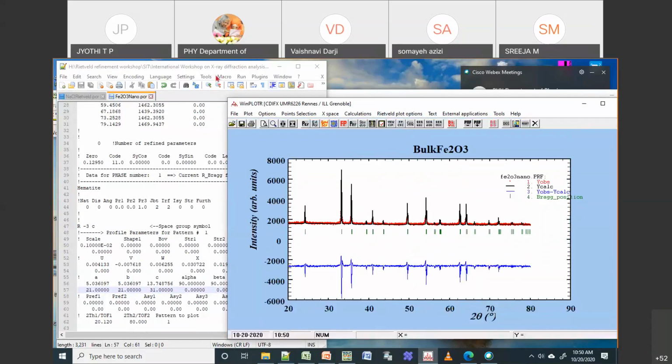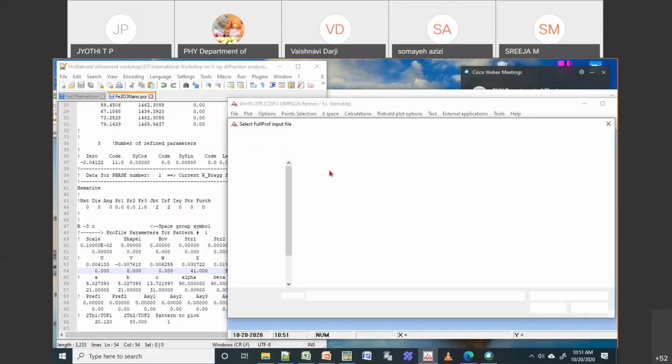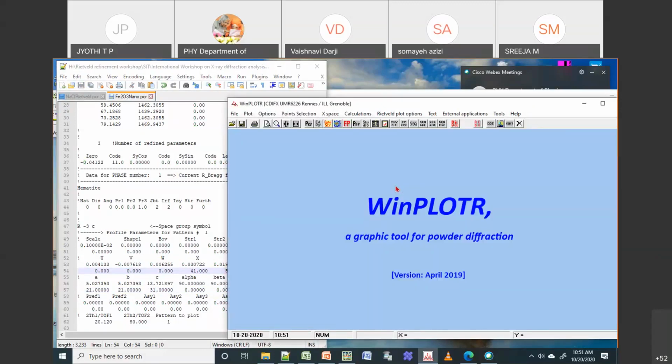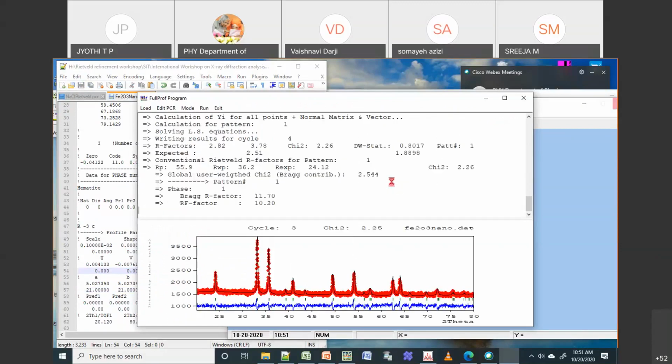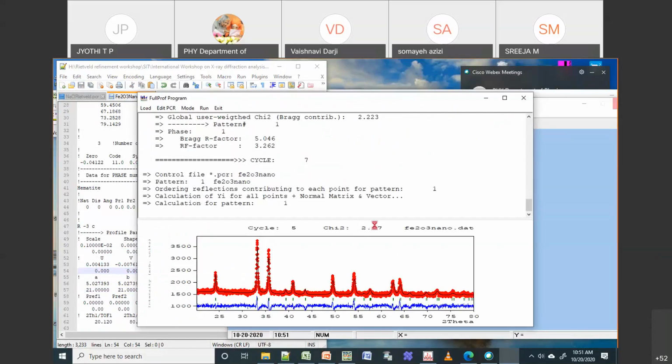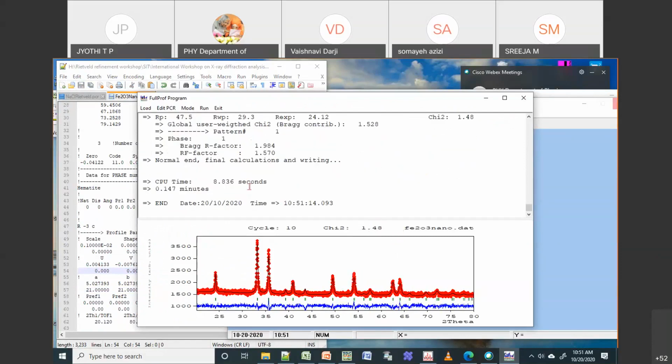How to change the shape is, you just have to change the x and y. Either you can do it here manually, or you can do it in your EDPCR. 51, 41 and 51. So I'll just do both at once, but when you are doing it, you can do one by one. You can do only x, then only y. I'm just trying to make it faster. Now you can see it has come down. It has come almost close to 1.53 or 1.48.